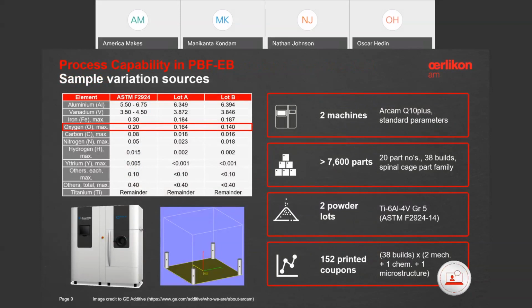To reduce the number of variables, we only considered 2 different powder lots in this study, Lot B and Lot A. As shown in the table, both powder lots had chemical compositions to ASTM F2924 with oxygen levels between 0.14 and 0.16%. After printing, the parts were post-processed in a blast cabinet, also known as the powder recovery system, hot isostatically pressed, and then ultrasonically washed. So important to note here, all the material we will present relates to the HIP condition.